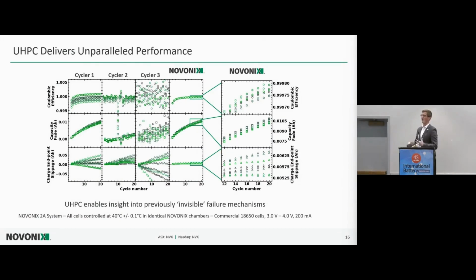And so what this turns into, when we take all this raw data, we integrate it, we start integrating all of those uncertainties, maybe those biases between charge and discharge. So we're consistently maybe overcounting or undercounting. We see that turn up in coulombic efficiency. These are 8 or 9 identical cells. And so we see pretty good precision and resolution, but very poor accuracy between all of these cells. And then these other 2 cyclers, not so great.